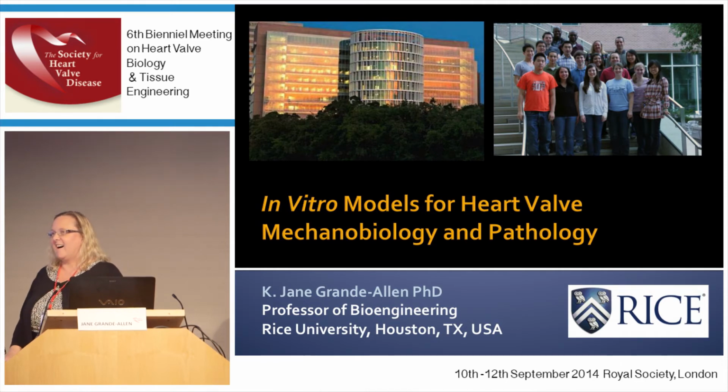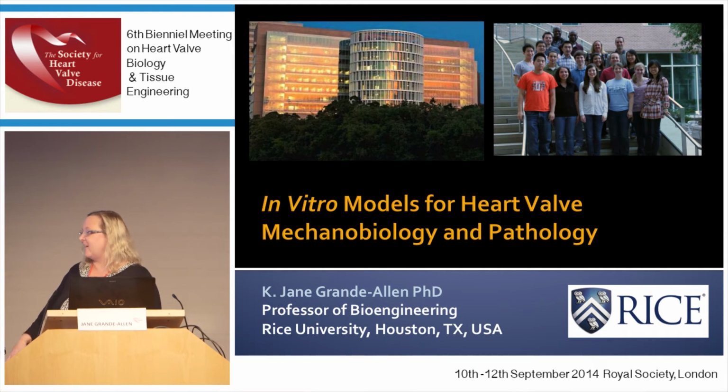Is that important? That's an interesting question, and I would really like to follow up on that. We're sort of doing that work now, because there are limitations based on the way light penetrates through them, so that influences how much patterning you're actually able to achieve that has a mechanical impact. And so this is why multi-photon confocal based patterning is maybe a better way to go if you do want to have a lot of control. But yeah, I think that the angle and thickness and length will be very interesting to follow up on. Thank you. Any other?